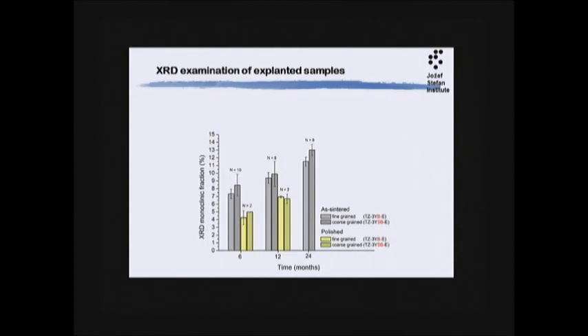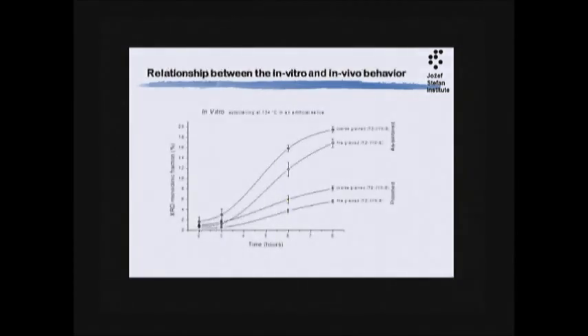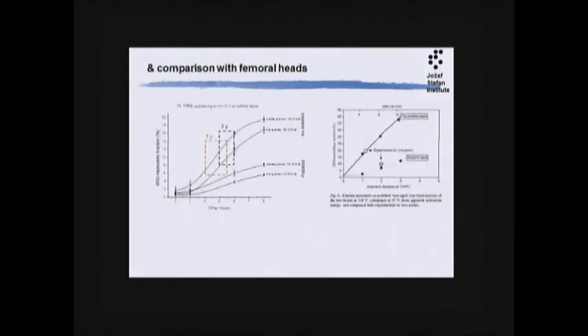I was shocked at the beginning, so we also inserted a couple of polished ones. 2 patients had polished specimens, and you see the amount of monoclinic on the polished is much lower than in this rough surface of the sintered material. And when we checked that, we had done in vitro experiments, we established this relationship. These are the experimental data from the in vitro experiments. And if we put the points from in vivo, we got this relationship. If we just compare these two, you see that they are quite different. The femoral head and this one behave differently.